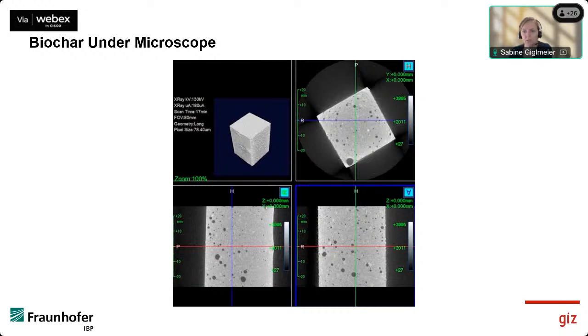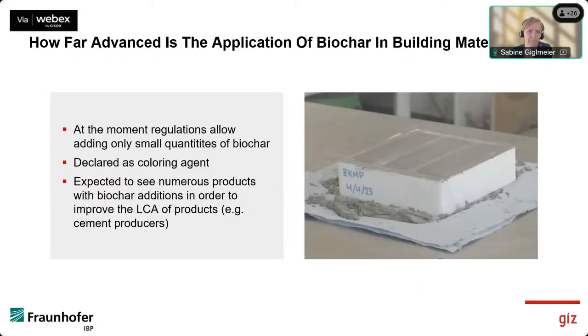This means that depending on the properties of the biochar, its addition in cement mortars is limited to a few percent. Up to 2% the changes are slight and even acceptable. At the moment, regulations allow only very small quantities to be added to mortar as a coloring agent. And in order to improve the eco-balance of a building material, the proportion must be increased.